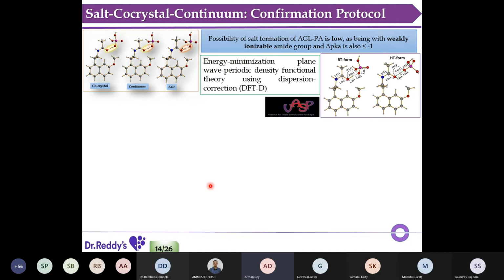So towards that we developed a computational methodology: energy minimization using plane wave periodic density functional theory. It's actually a dispersion-corrected DFT, it's called. And a VASP program we have used for this. And what looked very surprising, when we started to optimize the structure, we see for RT, the room temperature form, the phosphorus proton is shifted to the amide. And correspondingly the resonance structure also changed. That's why the CO bond distance, CN bond distance, and all these things changed.